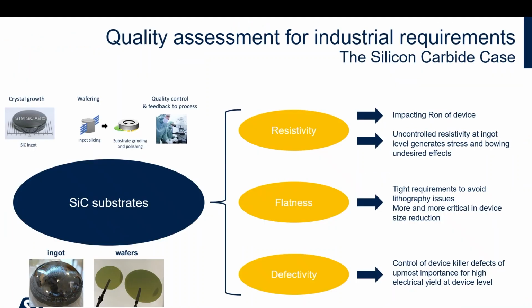So for silicon carbide manufacturing, you need to do something that is not done anymore by semiconductor makers, which is controlling the defects and the properties of the substrate. Because depending on how you grow, you can have an effect on the resistivity along the boule, which impacts resistance, but also the distribution of stress in the boule itself. You have to control the flatness, because if you don't have flatness, then when you go to the front-end process and the lithography, you have a problem with the focus of the optical lithography, and you have, of course, to control the defectivity. So you have to make specs that allow you to yield your device.